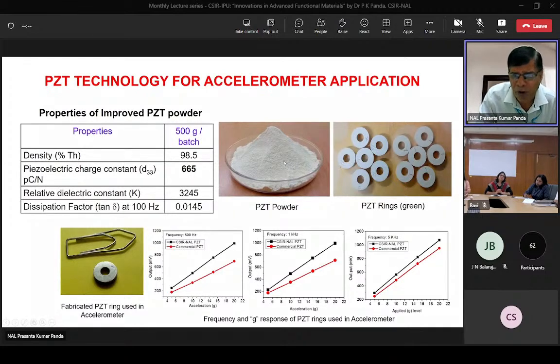And what is this technology? It is to prepare the PZT powder, and PZT is nothing but lead zirconate titanate: lead oxide, ZrO2, titanium oxide, and some dopants. So it is a multi-component material, and what comes out finally is a uniform, very fine powder having particle size less than 1 micron, that is 0.7 micron. Finally, we developed this material which after sintering gives about 98.5% of theoretical density, and the charge generated is very high, 665 picocoulomb per Newton.